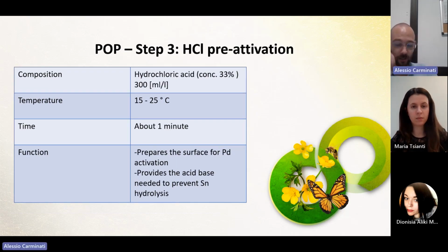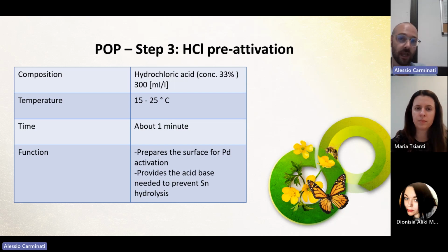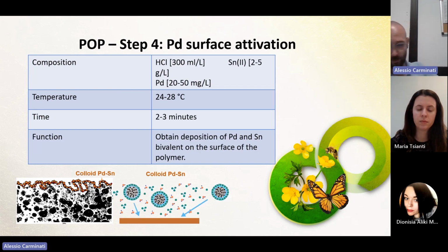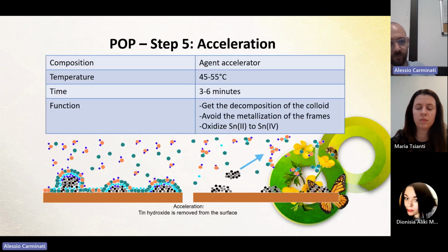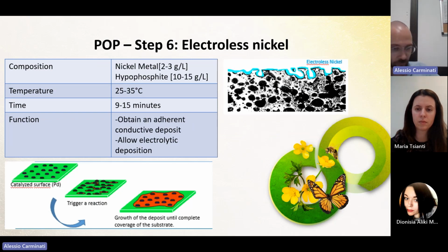So the next steps are a preparation with hydrochloric acid, and then an activation with colloidal palladium, which is not very economical, but right now is the most used solution for the activation of the surface, and of course also because it's a very good activator of the surface. And then some other steps that involve the final activation and the plating of the plastic.